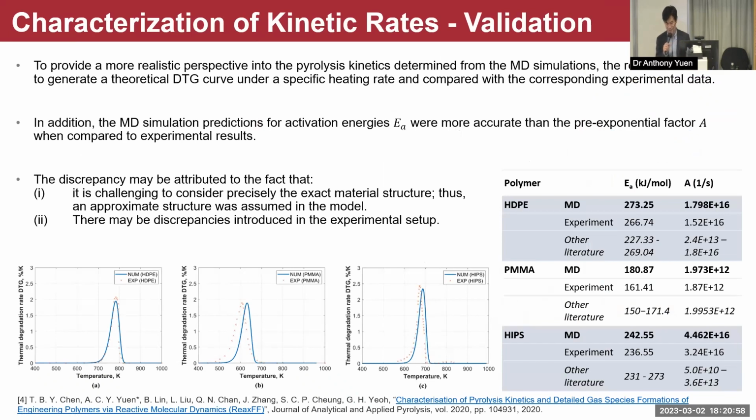So you can see for simple polymer structures, the result agrees quite well with the experimental rate, say 273.25 for activation energy for HDPE against 266.74. So it's just maybe 5 to 10% off, but it's pretty good in terms of accuracy.